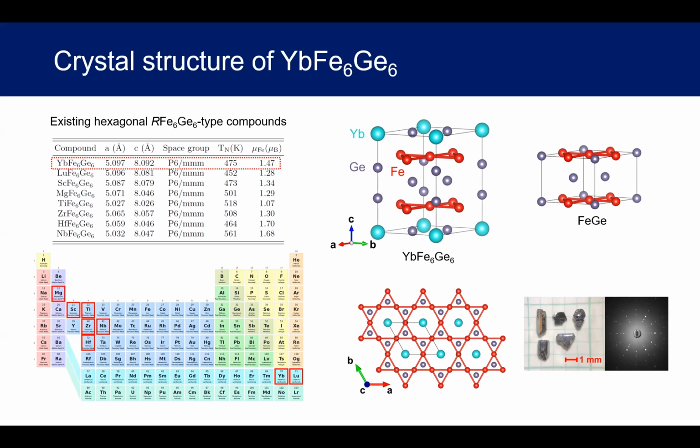My question is, you have these 3+ valences, let's say at A sites, and then magnesium, titanium, zirconium, which will all be nominally 4+, hafnium and niobium, maybe nominally 5+. This is very strange, that you can put these very different species all sharing that site, and I wonder, is there any understanding of this? Yeah, but I think, as Professor Wilson answered for the question, it is a covalent system. So maybe you cannot use a full ionic picture to understand this structure. But even in size, they're pretty different.